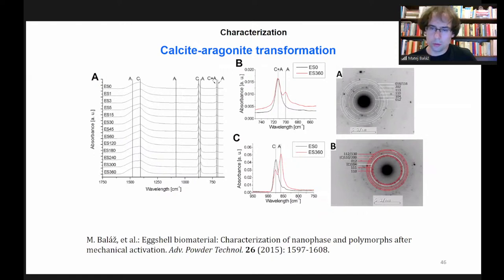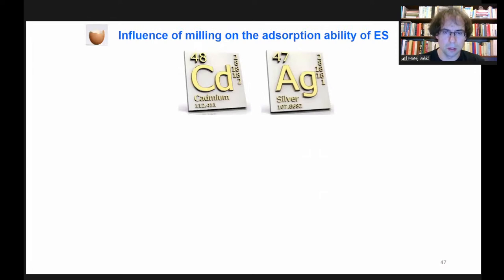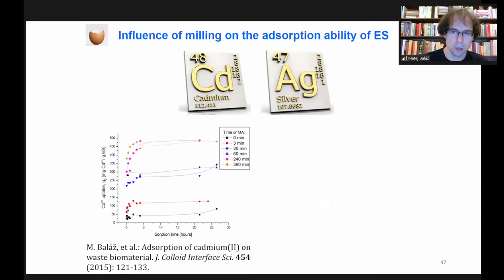Here is just another proof, by selected area diffraction, that we actually transformed calcite into aragonite. These red rings correspond to the aragonite phase. So we have used this milled eggshell for the adsorption of heavy metals. We selected cadmium and silver. In the case of cadmium, you can see the red line, which is the eggshell treated for just 3 minutes, and we observed the adsorption ability towards cadmium increased more than twice, and further processing led to a really numerous increase in this ability.